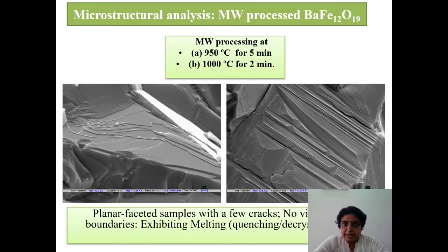Now I'll be coming to the processing at 1000. We have seen no XRD peaks. So all these striations are there, the signature of melting and quenching of the sample from very high temperature, because the moment we switch off microwave power, it's inherent quenching. So due to the quenching, the grain boundaries melted together. Here it's like some liquid is flowing, very interesting again.